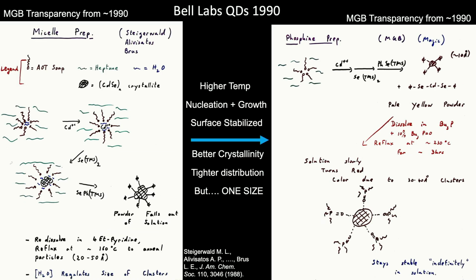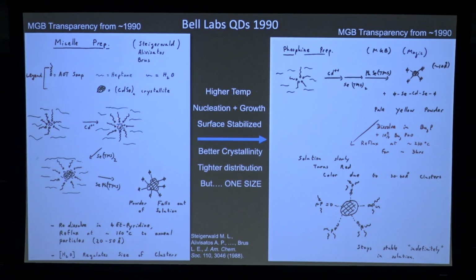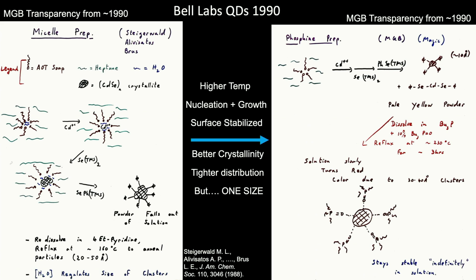And I've got a couple of transparencies from that time period, from 1990, after that observation, that describe the initial preparation that Mike Steigerwald and Alivisatos and Brus had come up with, the inverse micelle prep, basically growing little particles in water. This is a little bubble of water surrounded by soap molecules in pentanes and hexanes. So you add a little bit of cadmium, and because it's a little bubble of water, maybe tens of nanometers in size, you have a few atoms of cadmium. Then you add a selenium precursor, bis(trimethylsilyl)selenide, that reacts with the cadmium, and you form this very defective, very ugly sort of particle, misshapen, just like it is in my transparency here.